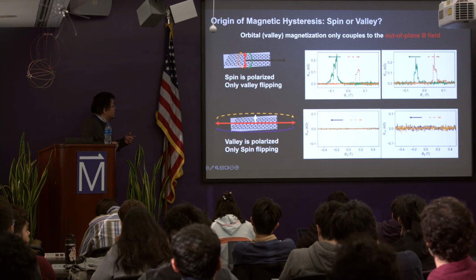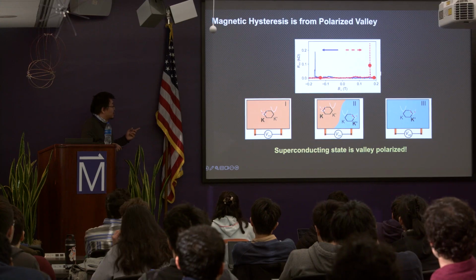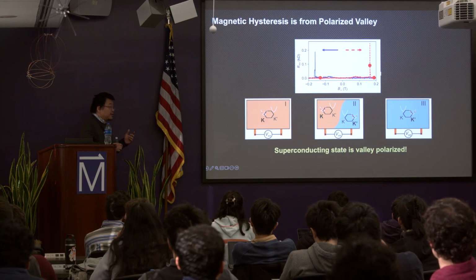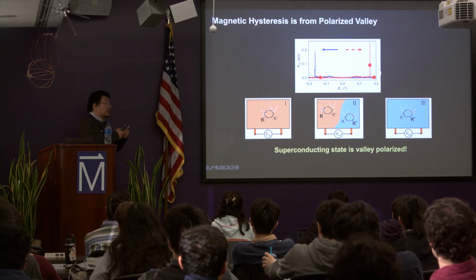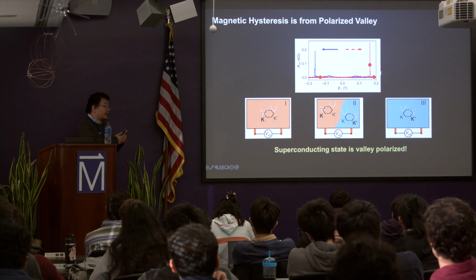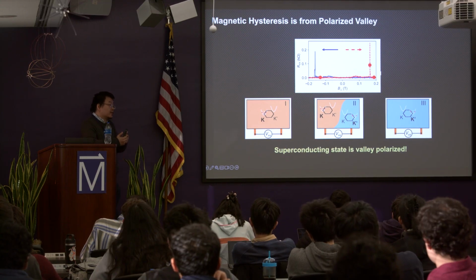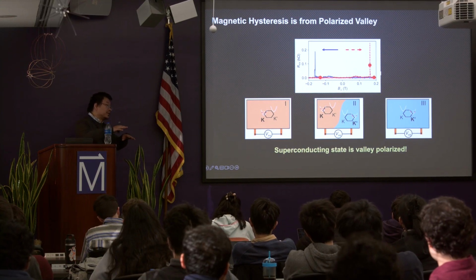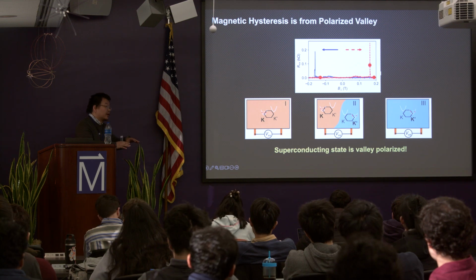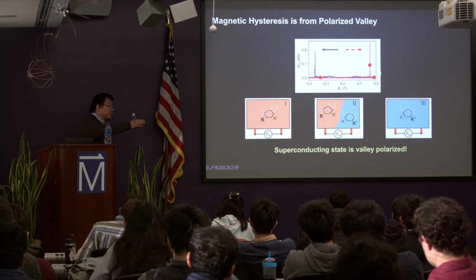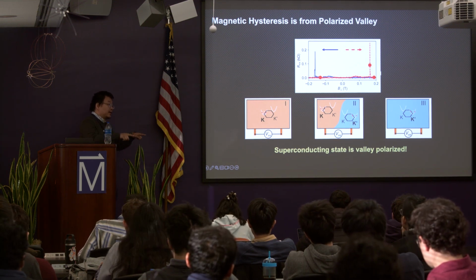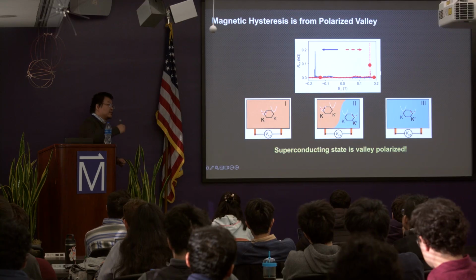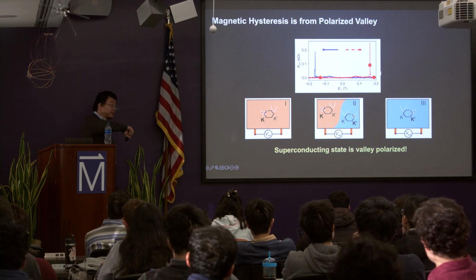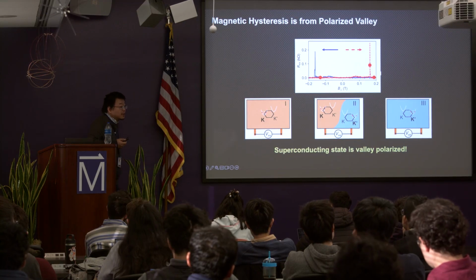Yeah. So actually the naive picture is, you have the superconductivity pairing within a single valley. So it's either from K valley or the K prime valley. So you have multiple domains in the zero field in the sample. And if you have a domain wall that is across the sample, then when you are measuring the resistance, that will give you a finite resistance because flipping the valley will cost energy.